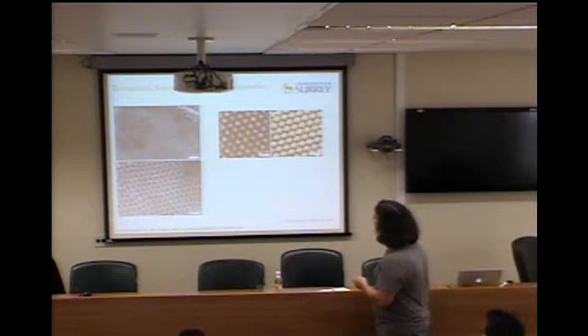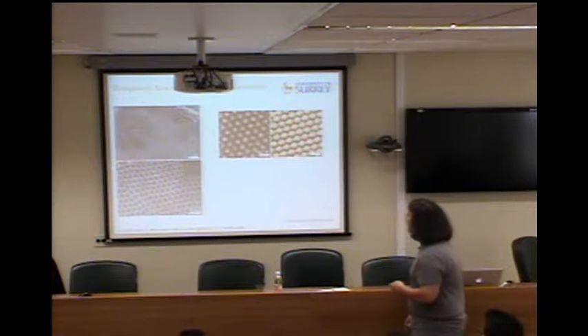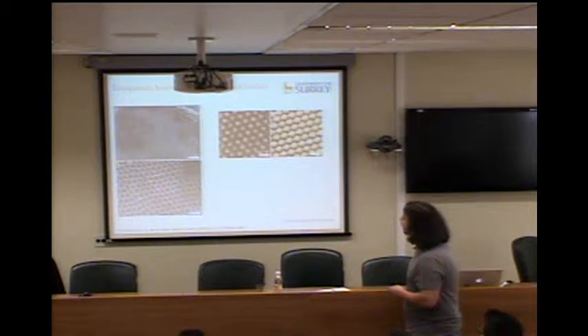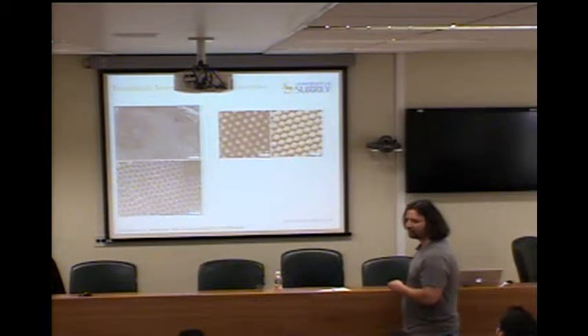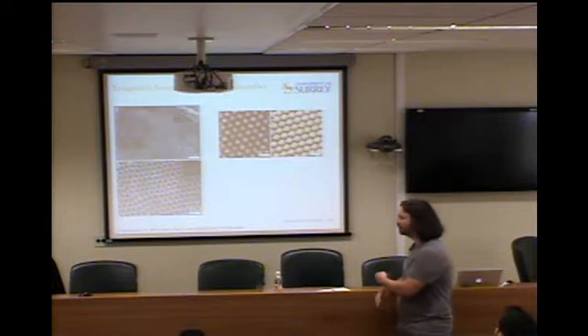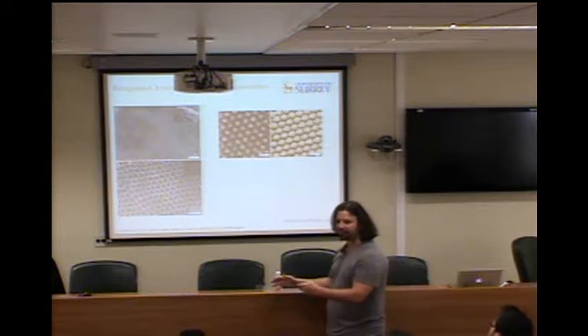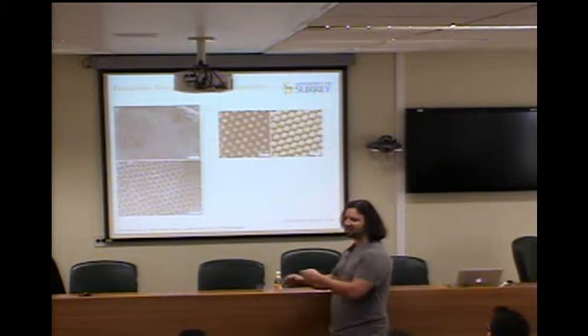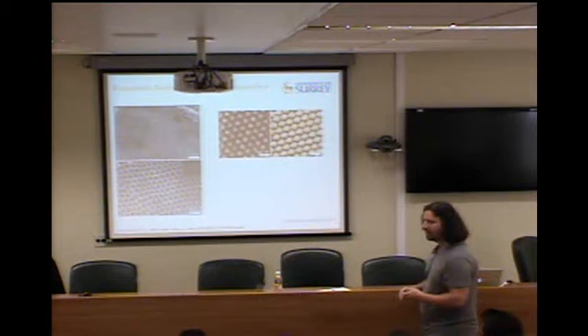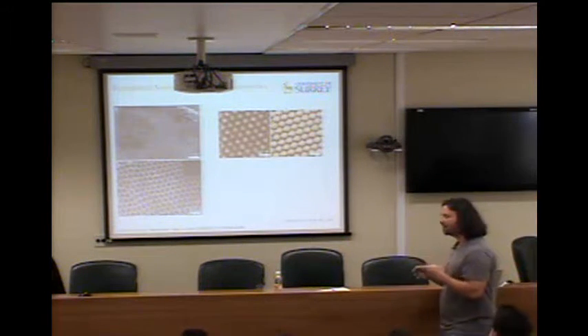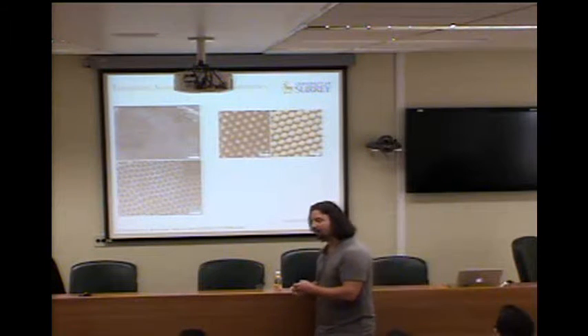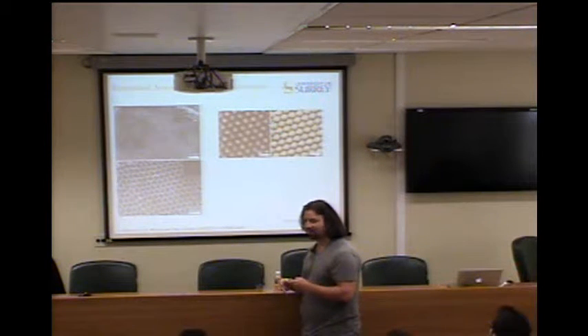This is an SEM image, roughly, I don't know what that is, maybe 15 microns across. And what's happening is the polymer particles are coming together, and they're forcing the carbon nanotubes to assemble into these hexagonal arrays. And this is truly large-scale self-assembly. We're showing this happens on centimeter, bigger scales. It's because we're playing off the temperature in an aqueous environment in a very similar fashion to natural self-assembly.